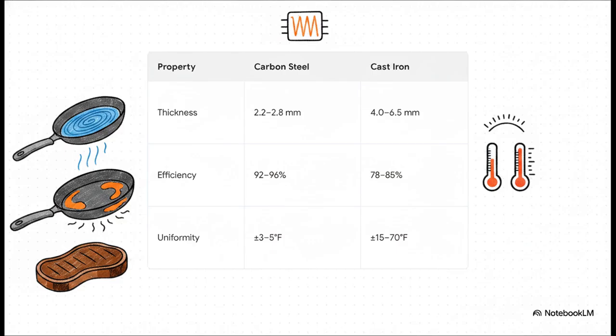Just look at the temperature uniformity after a 2-minute preheat. Cast iron can vary by up to 70 degrees Fahrenheit from the center to the edge. That's exactly how you get gray meat next to burnt edges. Carbon steel, on the other hand, is thinner and has a near-ideal magnetic permeability. Its induction coupling efficiency is an incredible 92 to 96%, keeping the temperature uniform within just 3 to 5 degrees. So carbon steel is what gives you that empirically validated, predictable heat distribution.